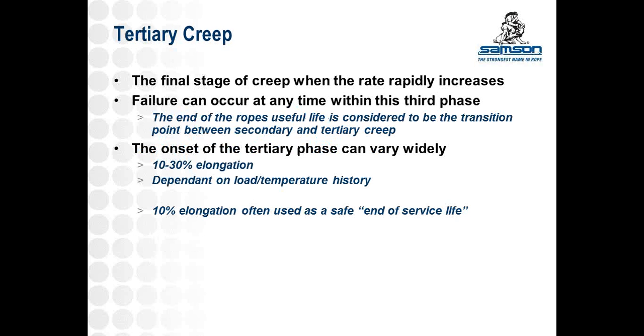And finally, as you hit that tertiary stage, this is where, as I said, the creep rate begins to pick up. And really the point of failure is oftentimes hard to predict. It can happen kind of randomly within that tertiary zone. But generally we say that once you've reached the onset of that tertiary zone, it's done. It's end of service life. And this tertiary phase can begin anywhere between 10 and 30% of elongation due to creep. Therefore, the safest thing to say is if the rope had gotten 10% longer than it was when it started, it's done. It's good to say you can put this away.